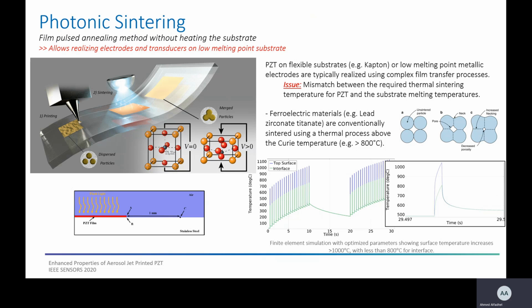And there is, of course, room for even more improvement. The range from 800 degrees and above has also been demonstrated to be sufficient to fully sinter the film, which is what's required to obtain the maximum performance.